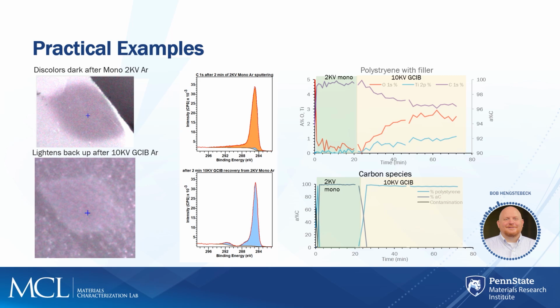And I'm going to sputter it initially with the 2 kV standard source, which is a single argon ion hitting the surface. And you'll see in the picture to the left that the sample right away went from being this whitish color to this dark color. What's happening is we're actually taking that polystyrene and turning it into graphite or a graphitic carbon. And that's actually what's shown in the middle picture.